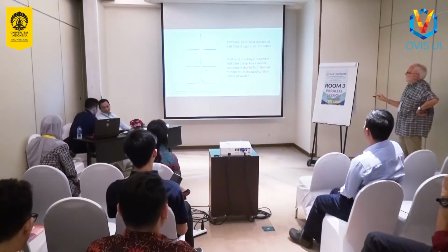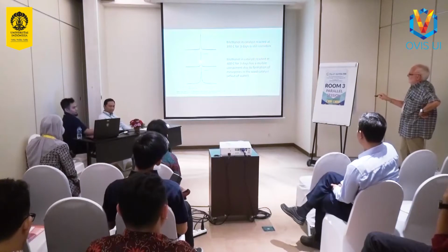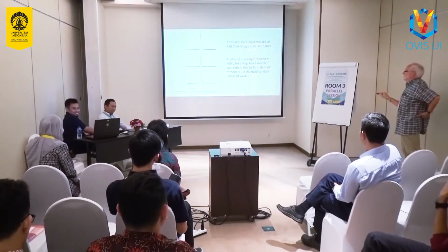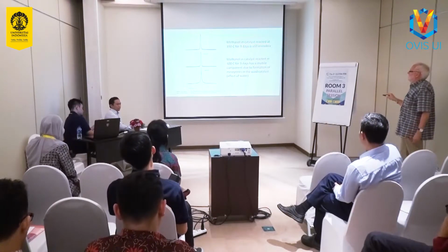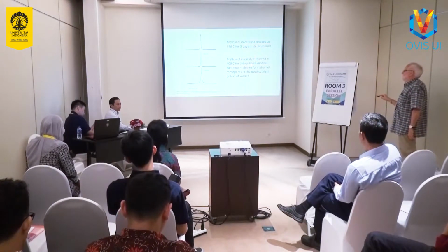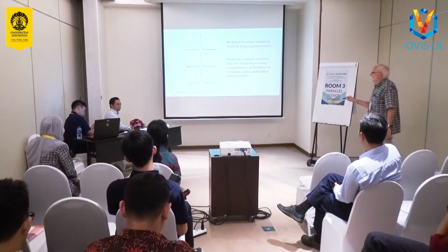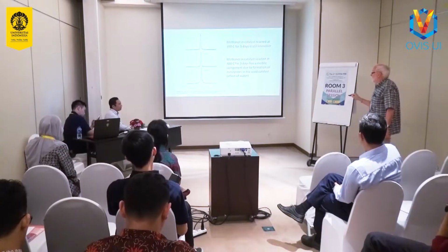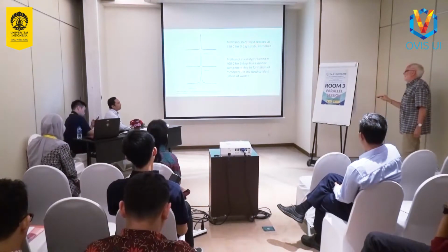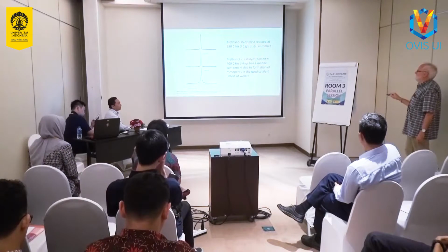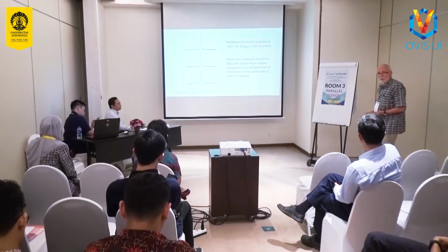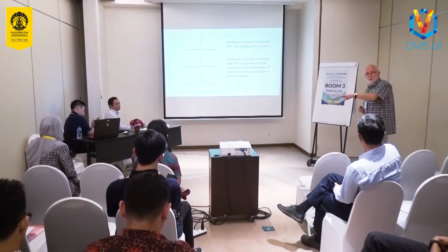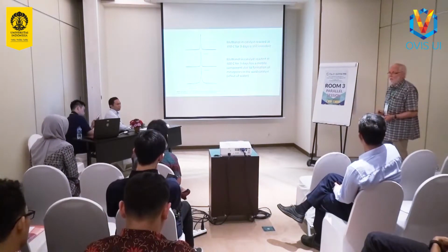There's no broadening. Likewise, there's no broadening here in this spectrum of methanol from the catalyst that reacted at 350 degrees for 3 days. But if we take the catalyst which has been reacted at a higher temperature and put methanol in, now you see the peak is increasingly broad. And we know why that is: at high temperature, we're making hydrocarbons from methanol, we're producing a lot of water. And water at 400 degrees will start to react with the zeolite lattice and cause hydrolysis.